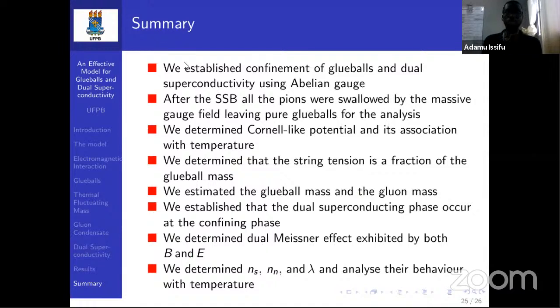Summary: we have established confinement of glueballs and dual superconductivity using Abelian gauge. After the spontaneous symmetry breaking, we observed that all the pions were swallowed by the massive gauge force, the dual gauge force, leaving only the pure glueballs for our analysis. Then we determined the Cornell-like potential and its association with temperature. We determined the string tension as a fraction of the glueball mass.